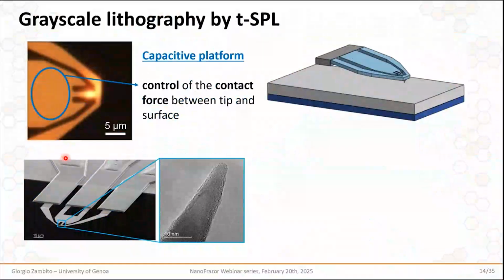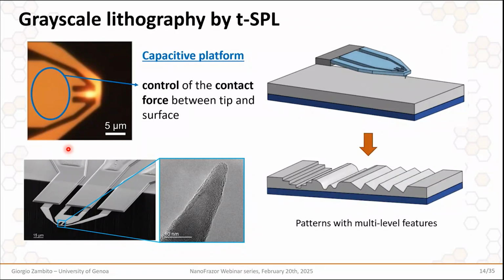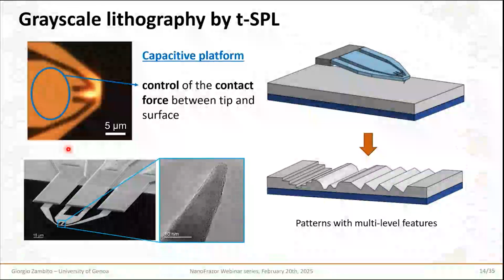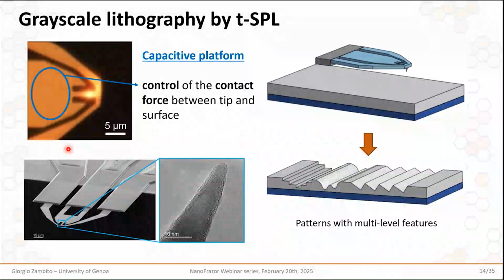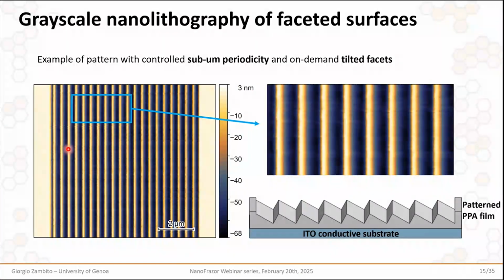So just to recap, if you're not familiar with the idea of grayscale lithography by NanoFrazor, by thermal scanning probe lithography, the idea is that the central part of the cantilever of the NanoFrazor works as a capacitive platform. This means that if you employ a conductive substrate, you are able to gain a high degree of control and high precision in terms of depth, not only lateral resolution. This means that you can devise and project some three-dimensional landscape, and you can reproduce them on the nanoscale with this kind of approach on conductive surfaces. And in our case, we exploited grayscale lithography to achieve patterning of faceted patterns with sub-micrometer periodicity.